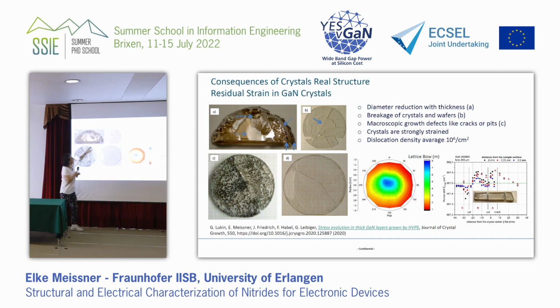So here you see different types of gallium nitride crystals, and you say, okay, they can be very nice. So they don't have all these growth issues. You see that if you want to enhance the diameter, sometimes it happens that a facet growth appears, then your crystal looks nice, faceted and hexagonal, but this is not what you want. The crystals are heavily strained and they break and so on. Then you have to measure, for example, over the whole wafer area of the whole crystal, how the strain distribution is. In the ideal case, this is center symmetric, but this is not always ideal.